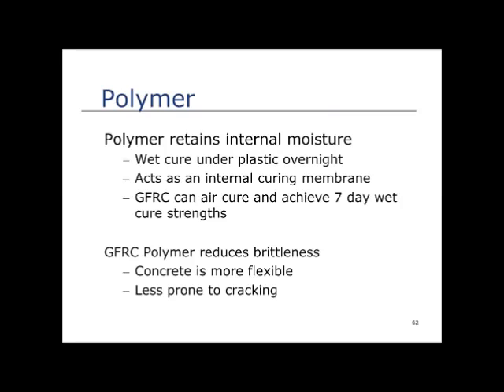Prior to the adoption of polymer as a key ingredient in GFRC, the big commercial GFRC factories would have to cast a piece and then wet cure those panels in a moist room for 7 days. So let's say every day they make 2,000 or 3,000 square feet of panels. Those would have to be put inside a big wet curing room, and then the next day's would go in, and the next day's, so they would have to stay in there for a week, and then they could be put on a truck and shipped off to the job site.